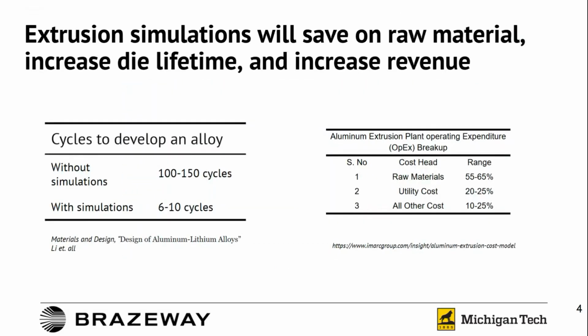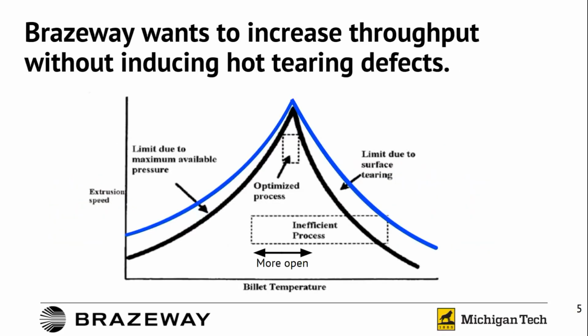Extrusion simulations will save on raw material, increase die lifetime, and increase revenue. It was found in studies that without simulations, experimental alloy development can take up to 100 to 150 cycles. With extrusion simulations, that was lowered down to 6 to 10 cycles. As well as that, being able to use extrusion simulations allows for a reduction in raw materials, utility costs, and production costs. Brazeway wants to increase throughput without inducing hot tearing defects.